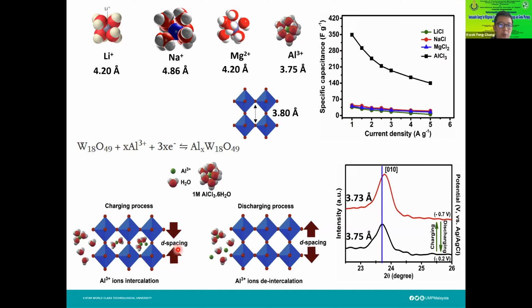And we tried XRD on the crystal, and we were able to find the d-spacing. How does the charging and discharging process work in this tungsten oxide material? Once the aluminum ion intercalates into the structure, we found that there's a contraction of the d-spacing. It gets reduced to 3.73. But when it gets discharged, the d-spacing expands. That has been proven by our XRD.